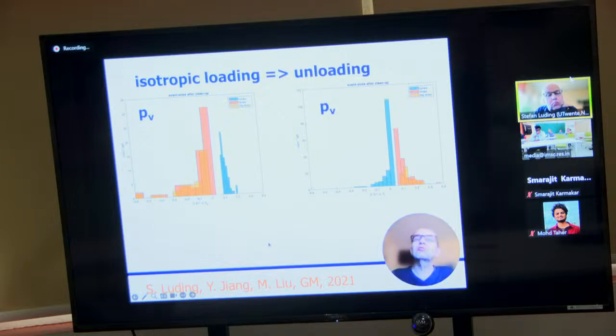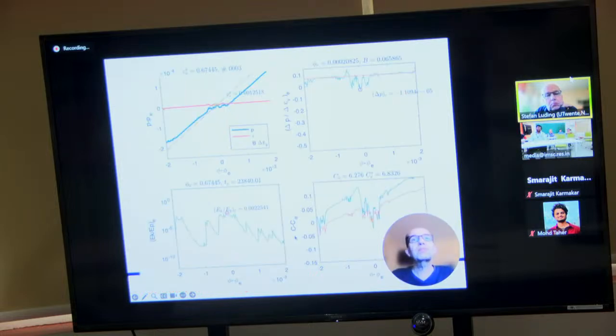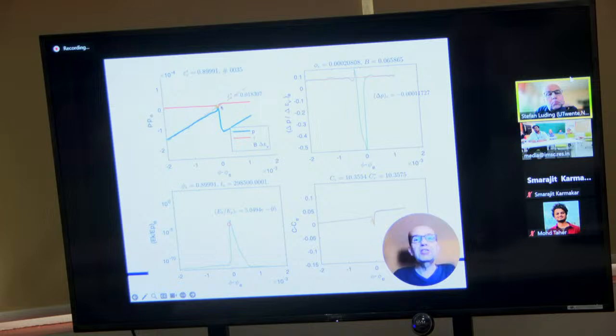And with this, the continuum theory is finished. Only the shear is not sufficient. We also need the isotropic events. Okay, and then we do the same as we did before for shear. We zoom into one event. Stress drop or stress fluctuations are happening close to jamming. Violent wiggles are happening.